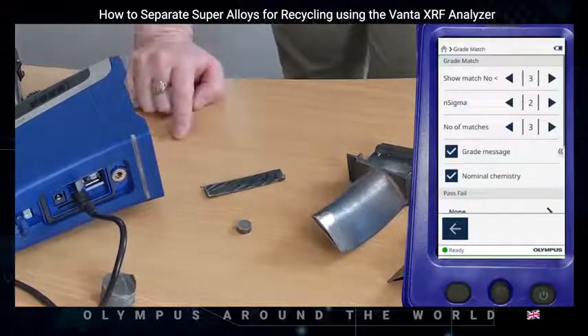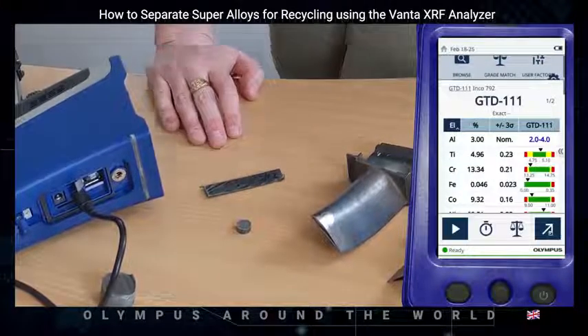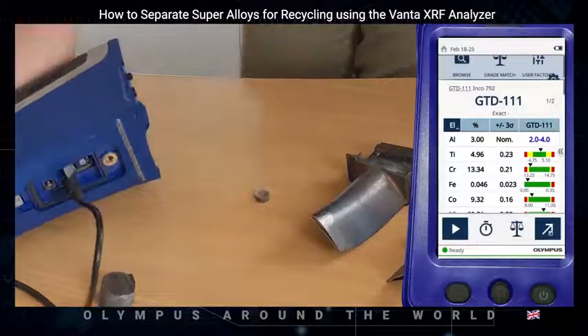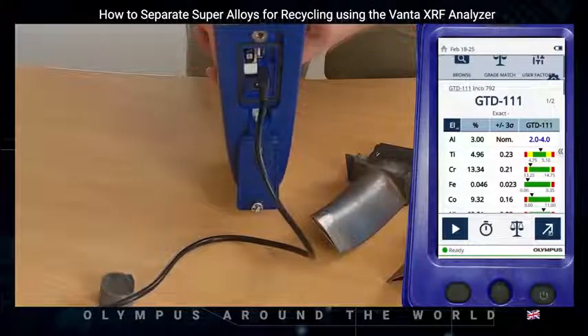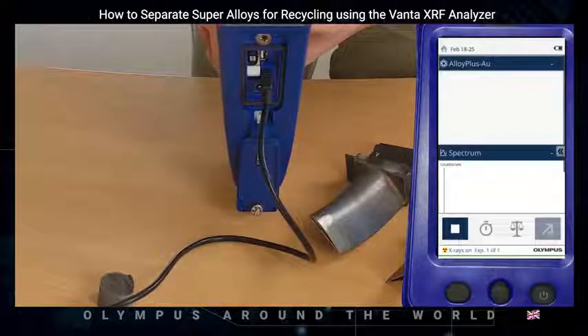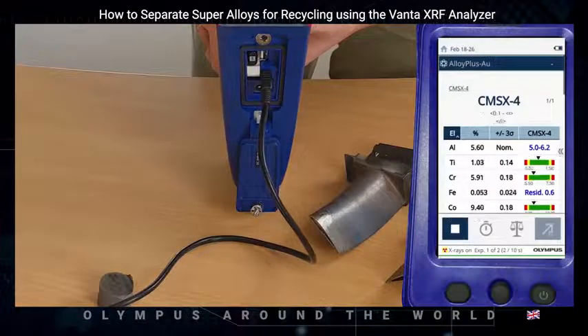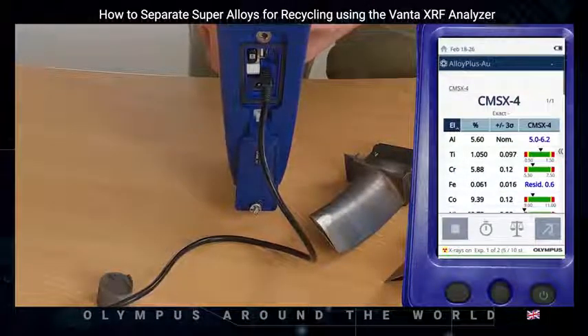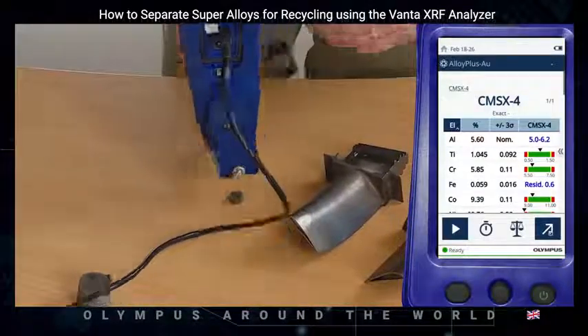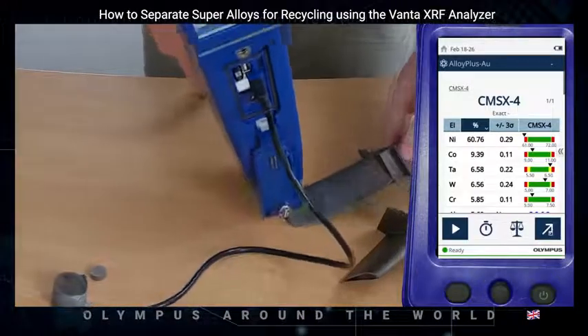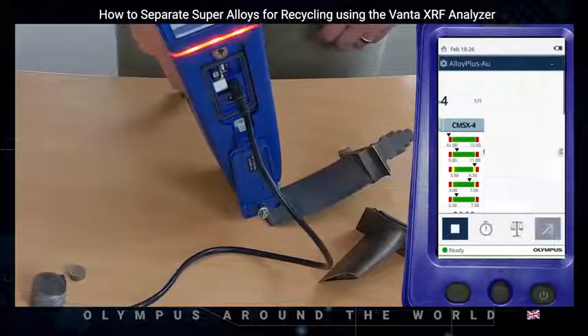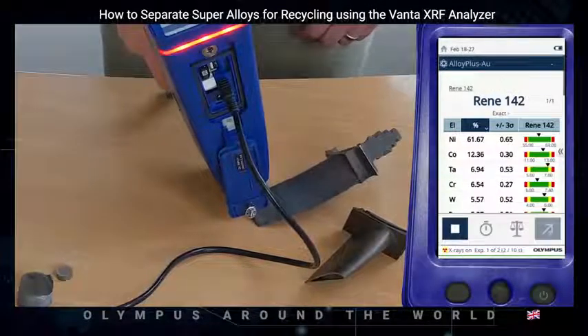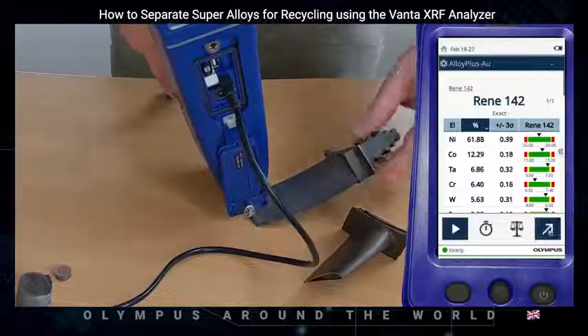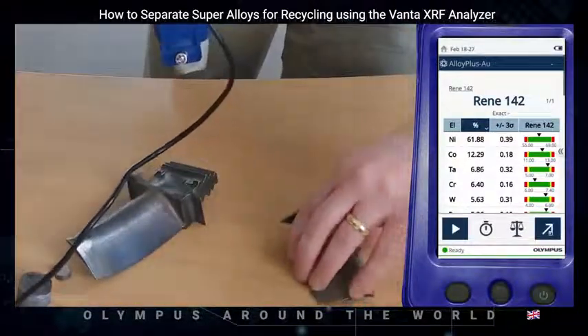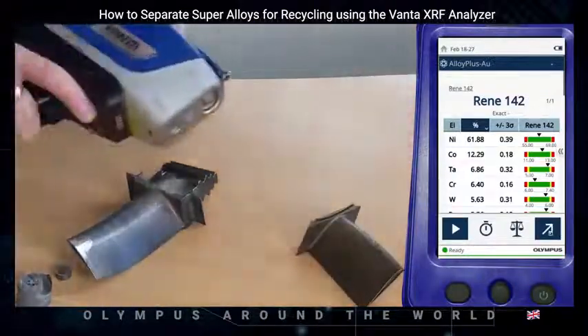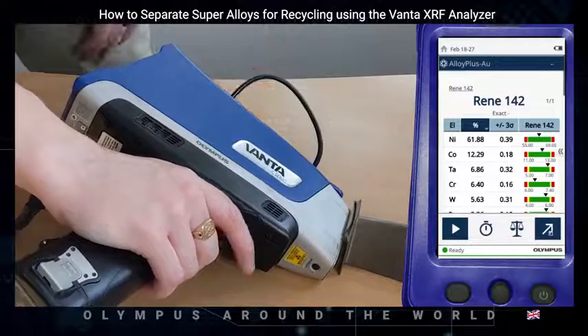So let's test these other samples and see whether we can get grade matches for these or whether the surface prep needs some work. Now this smallest one causes us some problems due to alignment, but as long as you get the sample central and hold the instrument still, we should still get a good result, and as you can see on screen, CMSX-4. This sample, the edge of the turbine blade, is quite difficult to measure, but as you can see, in less than 5 seconds we get the grade match. And sometimes you need to test with a slightly different orientation just to ensure you can get a result.